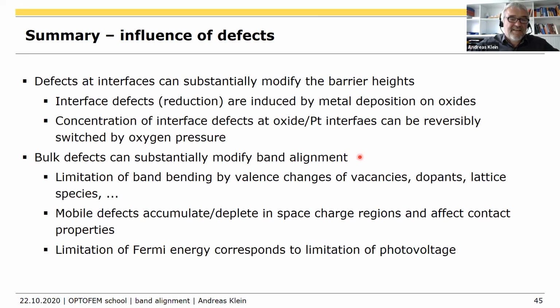A funny thing is that it does not necessarily have to be a crystallographic defect, because if you have these transition metal oxides and they change their valence, that is also to be considered as a defect. And these defects are present in huge concentrations. Every unit cell contains a defect. You have to think about this. So that can be quite a severe thing.